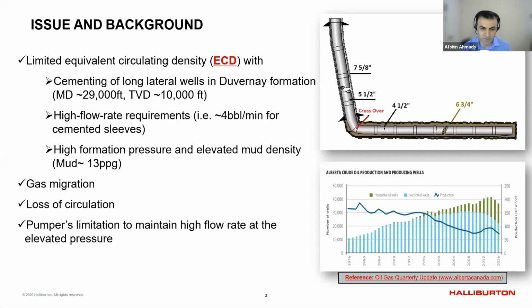If you just reduce the rheology, as I said, you're going to end up with a higher volume of cement getting lost into the formation. On top of that, there is pumper limitation. You don't have many companies, and there is a limitation on the pumpers' horsepower. You cannot just have a cement with any density or rheology and try to keep the pumping rate as high as possible. In most cases, you need to have double pumpers on location and pump the displacement simultaneously. That's going to be additional cost and complexity, and logistics are going to be more complicated.